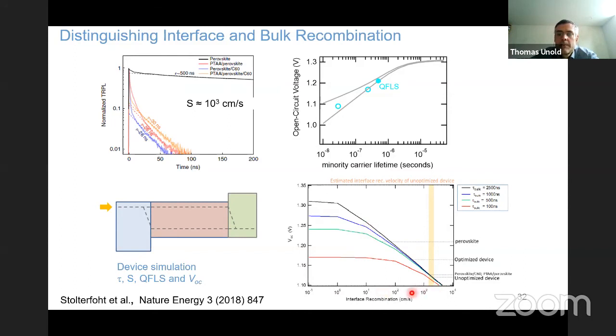But if your interface recombination is in the 10 to the 2, 10 to the 3 range, then your great material with, I don't know, 5 microsecond lifetime doesn't really improve the VOC of the device. And if you want to improve the device, you first have to work on the interfaces.